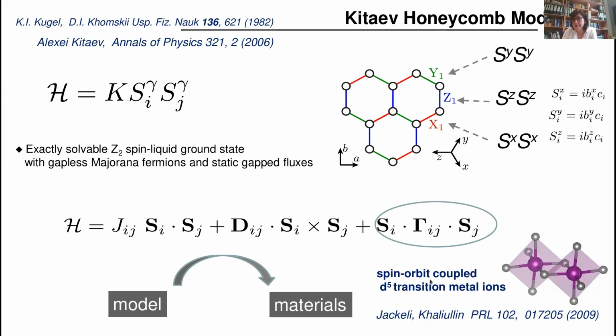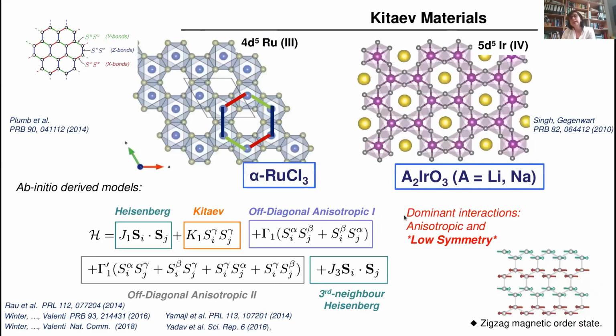By considering this type of construction, one can get this type of Kitaev interactions. Here are two of the most discussed materials that fulfill these conditions: defining a honeycomb lattice of 4D ruthenium in a filling of 5 electrons, with an octahedral environment of chlorine, by sharing edges. So what we did is use first principles calculations and then project into spin models.